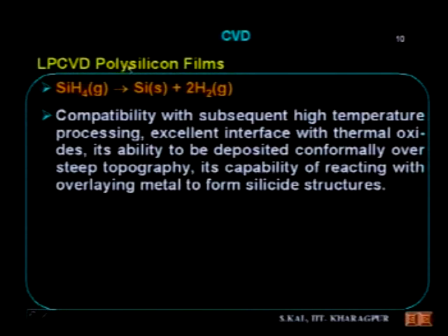Another characteristic of LPCVD polysilicon film is its ability to be deposited conformally over steep topography. This is one very important characteristic. Because if the surface topography is not plane, not uniform, there are a lot of ups and downs. Steep topography means there are certain regions which are depressed and certain regions which are elevated,